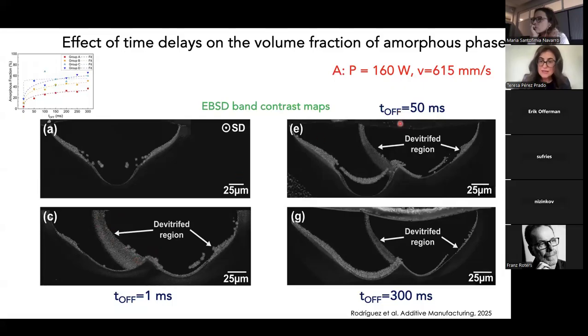What happens now if we increase the time delay? Well, you see that the width of this devitrification region decreases, especially when we go from 1 to 50 milliseconds, and it decreases slightly further when we increase the time delay to 300 milliseconds. So this is the idea, and this is why we are seeing this increase in amorphous fraction with time delay.